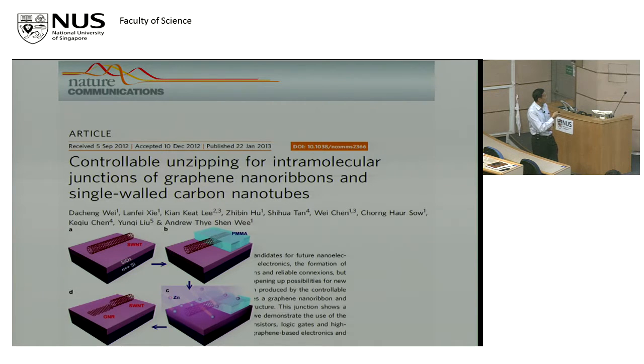Now, this method of unzipping a single-wall nanotube has been demonstrated before, but this time we unzipped it. You're basically sputtering it with zinc ions with the right momentum. You unzip it because a nanotube has a fixed diameter. It opens up to a fixed-width nanoribbon. And if you only unzip it partially, through masking part of it, you get a junction that has a single-wall nanotube, which is metallic in this case, and a semiconducting graphene nanoribbon.